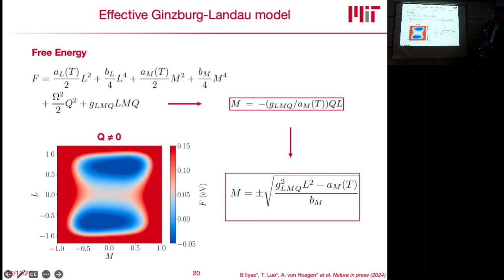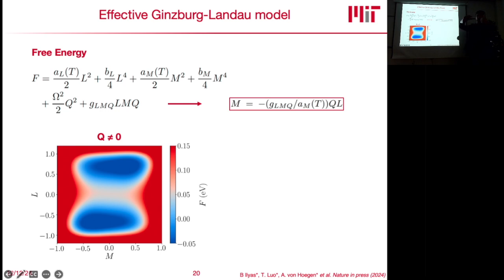In the end, the magnetization only depends on the antiferromagnetic order parameter in the system, and it depends on it as L squared. And L squared, close to the transition temperature, is basically the fluctuations of this order parameter, which at the transition temperature diverge. Can you remind what L is in that? L is the antiferromagnetic order parameter. So if you take the two sublattices and add them up with a minus in between. And M is just the magnetization, where you look at the overall magnetization of the system. So how much are these two spins imbalanced, basically.